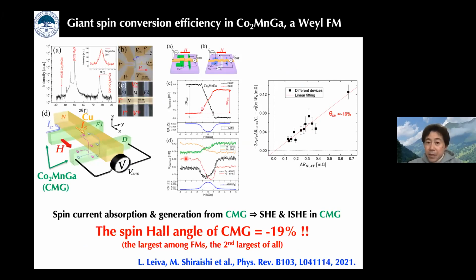And my group is also interested in other types of topological materials, and here I show one example. Here we reported the gigantic spin Hall effect, spin conversion, by using the cobalt manganese gallium, a Weyl ferromagnet. In that work, we used the CMG as a spin source and spin detector, and by fabricating such a non-local spin valve device, spin current is generated from one CMG electrode, and pure spin current transports in the copper wire and reaches the detector CMG electrode.